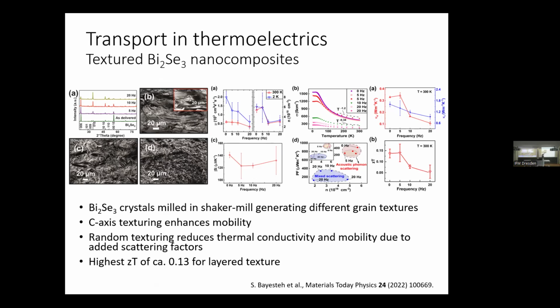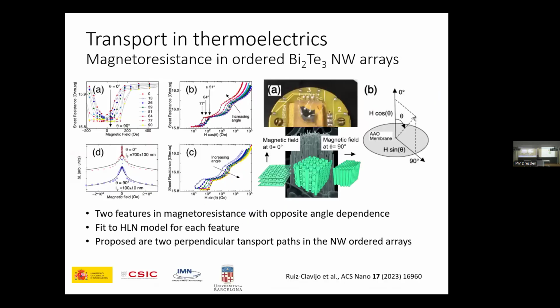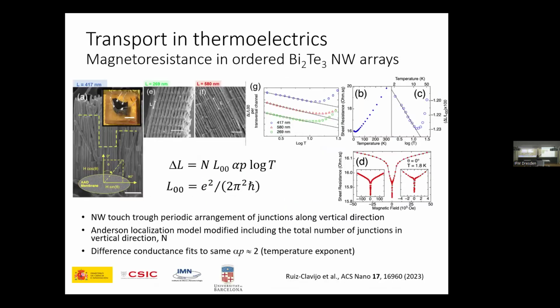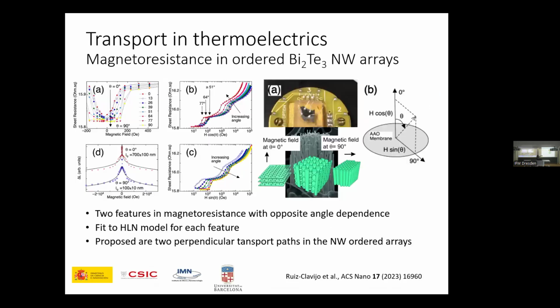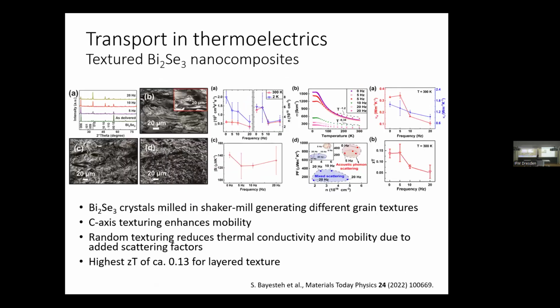So we measure the whole thing. We don't need to reduce the dimensionality. So it is strongly disordered. Yes, exactly. So phenomenologically, from the appearance of it, we see the same localization effects as you would see in a nanostructure like that. Well, not that particular one, but that same kind. And the key is to create that type of structure.